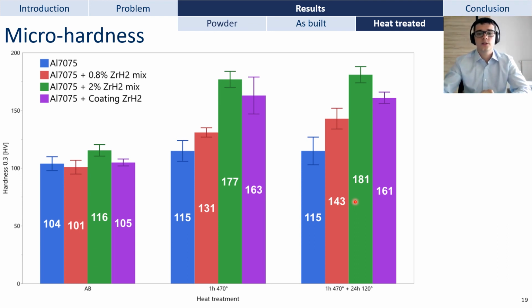Finally, we can see that the aluminum 7075 and the low zirconium content powder mix have a low value of hardness, which is not quite surprising because the microstructure was coarser and there remain some cracks inside the microstructure. And finally, the plasma-coated powder exhibits a lower hardness than the high content one, probably due to the fact that there were more fine equiaxed grains for the high zirconium content powder.